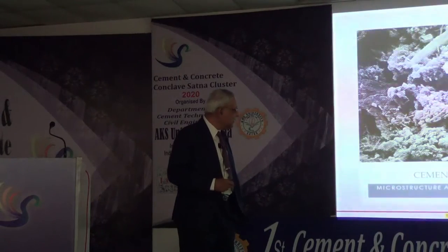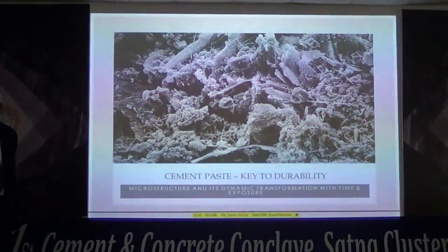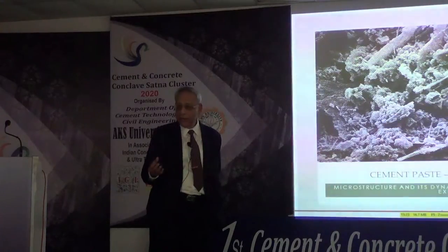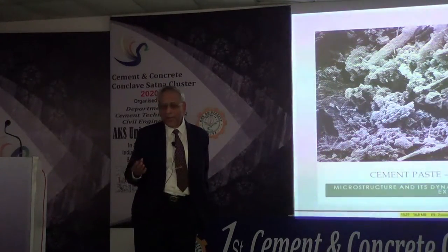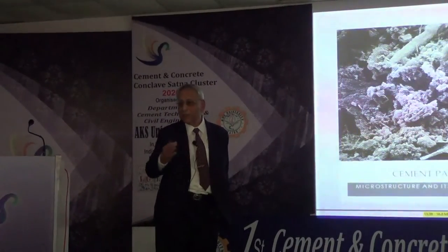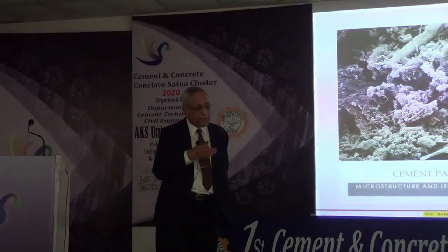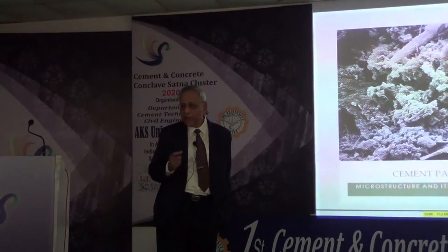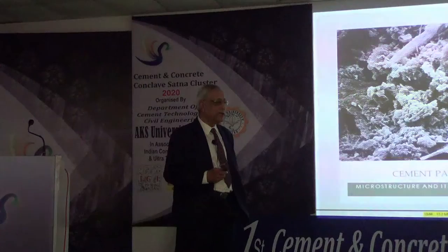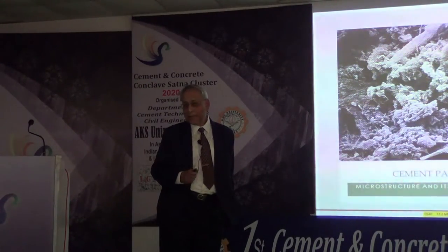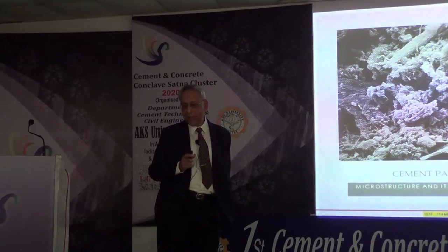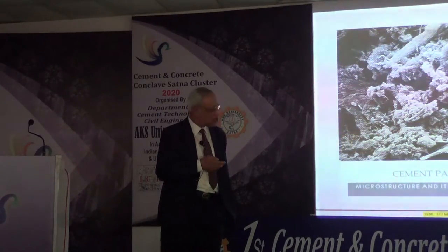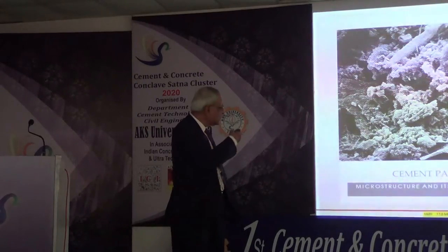If you look at that, the major issue is: in the concrete, what is holding the entire concrete? What is holding it is only anywhere between, say, 8 to 15% of cement that you have used. And what that cement has done is really react with water and create what we call the hydrated cement paste. And that's the critical part of the entire concrete making. That hydrated cement paste has two major components, as you can see from this